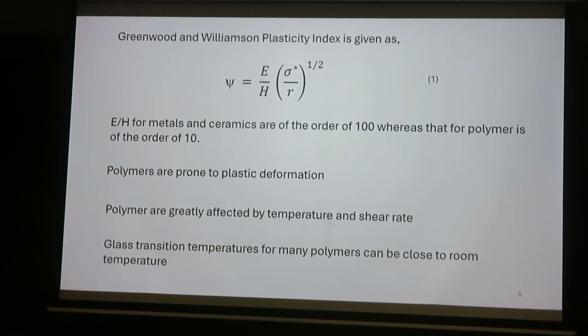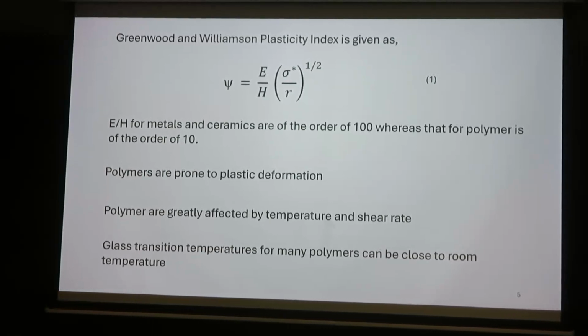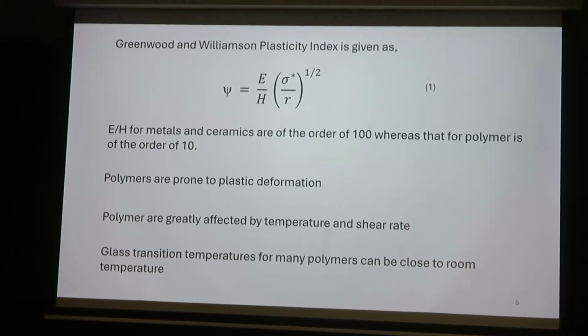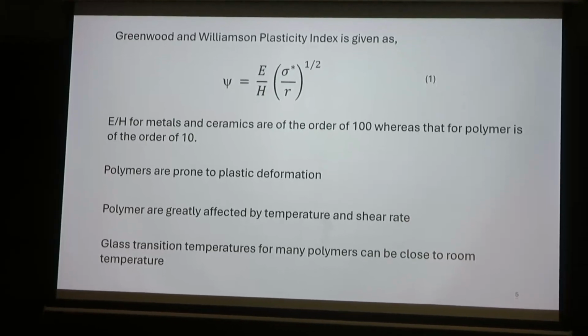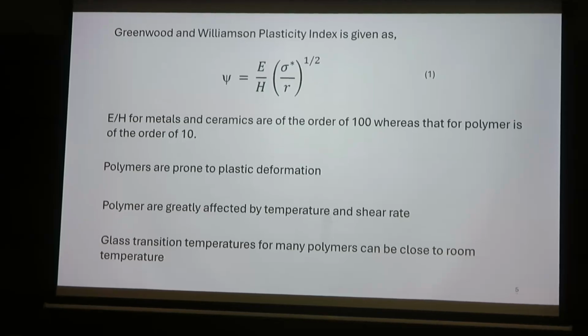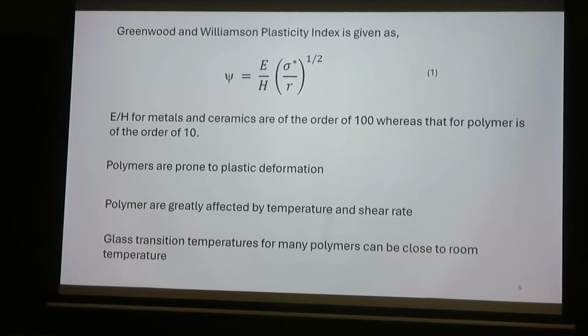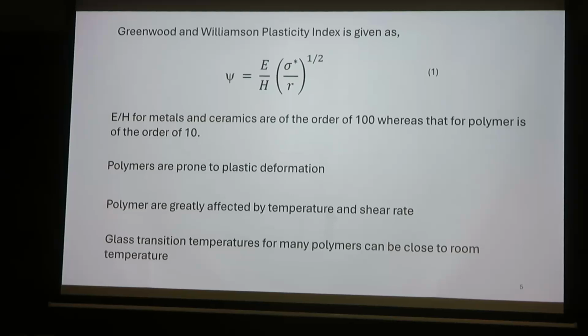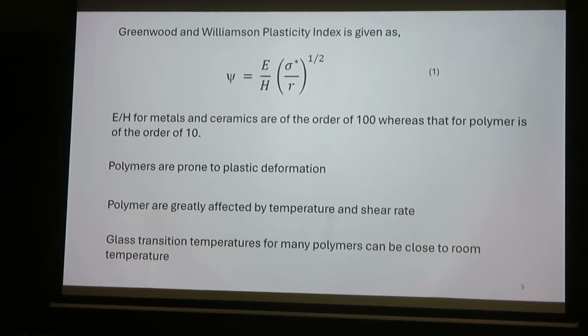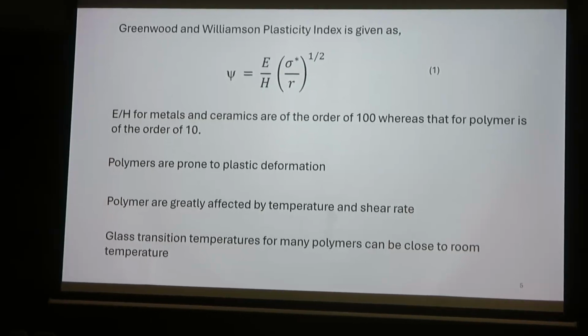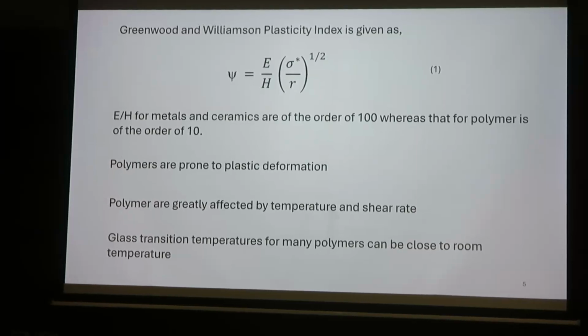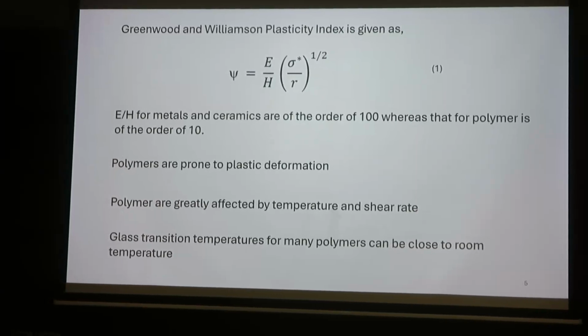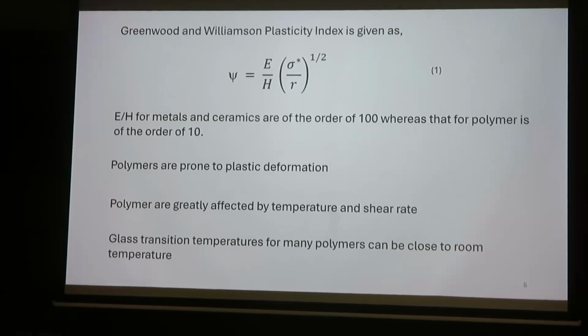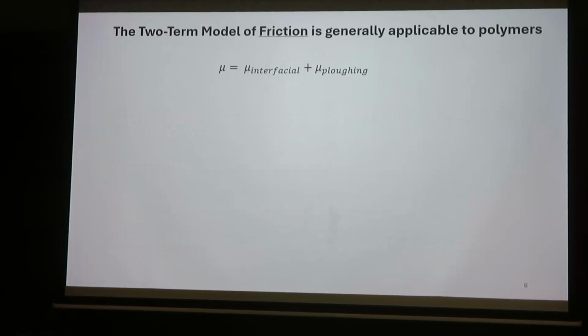And another thing is glass transition temperature. For polymers, it is very close to room temperature, and often they change quite drastically. So glass transition temperature is also very, very important, because this will determine whether the polymer is going to fail by brittle fracture or plastic deformation. So these are the important basics about polymers that we have to know.